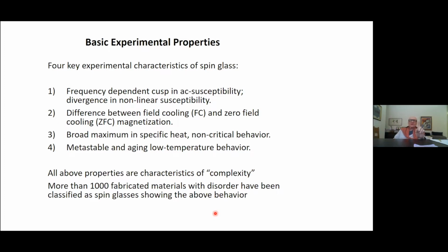So we have these 4 simple key characteristics of a spin glass: the frequency dependence cusps in the AC susceptibility, a difference between the field cool and zero field cool states, very, very different spin glass states, which depend on the order parameter that you measure with this type of field cooling. We are very lucky with the spin glasses. We have the conjugate field. This field is tunable.